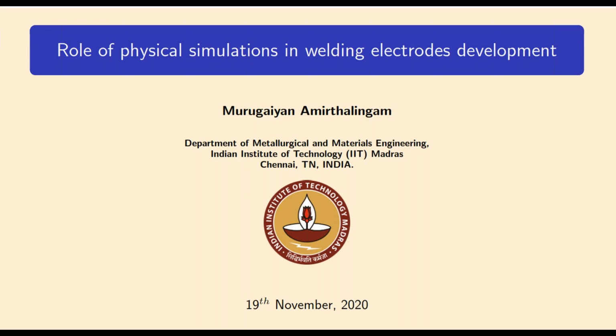So we can calculate the dilution fraction based on the welding process parameters that we use, and from the geometrical analysis of the weld when you make the weld in actual material. And we can get the final weld metal composition from the dilution calculations. So therefore, the exercise that we have carried out always involves a range of chemistries with the dilution factor in mind. Even if you have a large dilution or dilution is minimal, we'll be optimizing the electrode chemistries, so we can choose the electrode composition accordingly. That's the reason why we will not optimize only one chemistry. We'll be optimizing 3 or 4 chemistries, which can give us the microstructure that we want. Brian, I hope that answers your question.